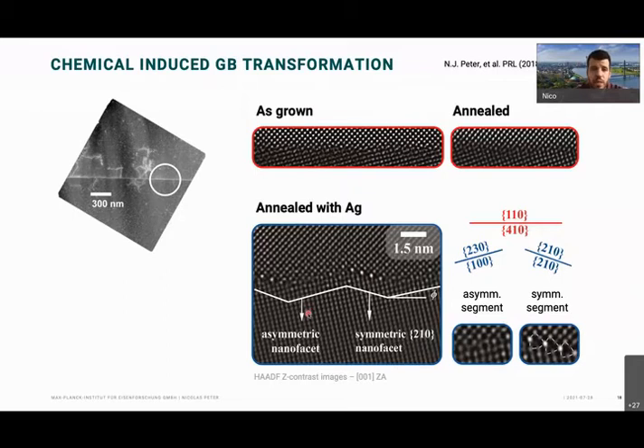And we can also look at the structure. So we find that we have an asymmetric nanofacet here, and then we have a symmetric 210 facet here. And this one is the boundary that I was talking about much before, which is a very common boundary, the symmetric 210 boundary in the sigma 5 system. The structure is shown here a little bit more in detail, and we see the silver always falls in these central CSL positions, as I mentioned at the beginning.